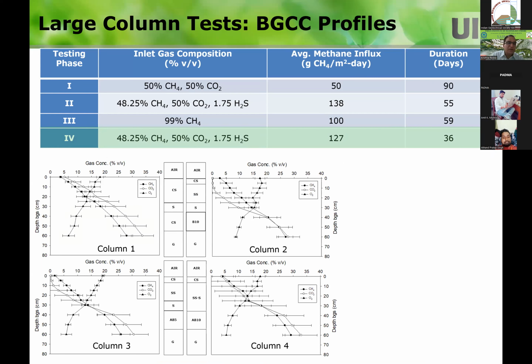Interesting things, let's look at column 1. You see, you have high concentrations of methane and CO2 throughout the column, and you can see high concentrations even at the top. But if you look at column 3, you can see that CO2 concentrations are higher at the bottom, but as it comes into the slag layer, you can see the concentrations are reducing significantly, and near the top you have 0 concentration. That means CO2 has been completely sequestered. Even methane concentrations have decreased significantly, and you have very minimal emissions at the top.